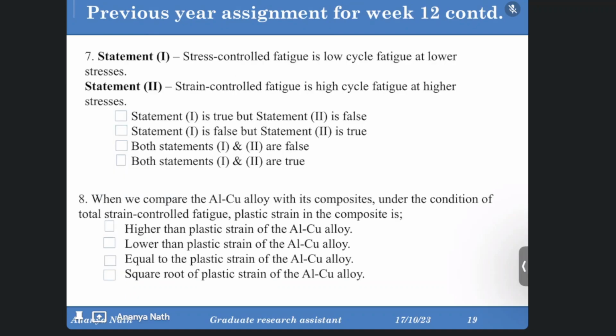Statement 1: Stress controlled fatigue is low cycle fatigue at lower stresses. Statement 2: Strain controlled fatigue is high cycle fatigue at higher stresses. Which is correct, which is wrong? I guess the first is wrong, and the second is strain control fatigue. If the first is wrong, then the second will also be wrong, right? Because there are only two types: stress control and strain control. And low cycle means higher stresses and fewer cycles, so the first is false, and low cycle with higher stresses means strain control. So both statements are false.